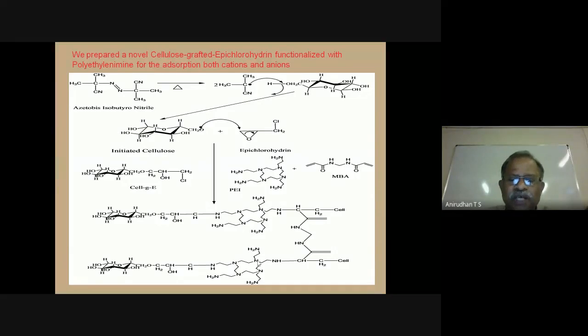So what I have concluded is that this material can be directly utilized to capture metal ions from the environment, and also converted into other cationic or anionic exchangers, these ion exchangers. Usually ion exchangers are prepared from materials having amino groups, because the amino group is converted into a COOH group or sulfonyl group after treating with succinic anhydride or that type of chemicals. And even simple treatment with HCl will convert it into NH3+ Cl-.